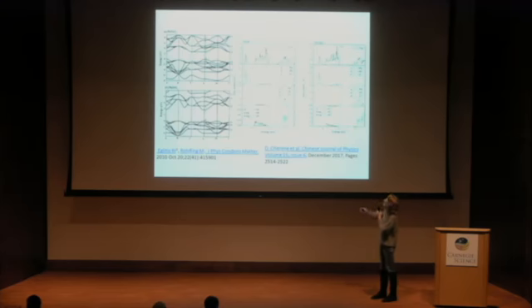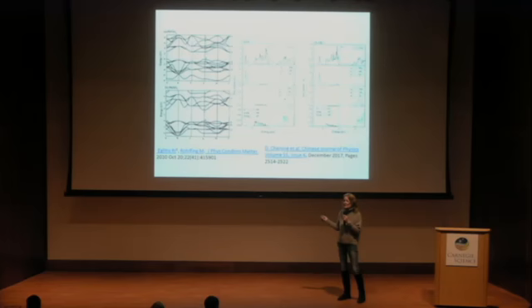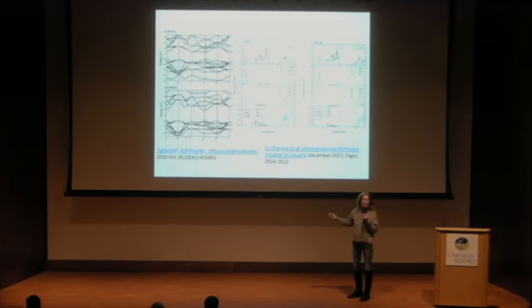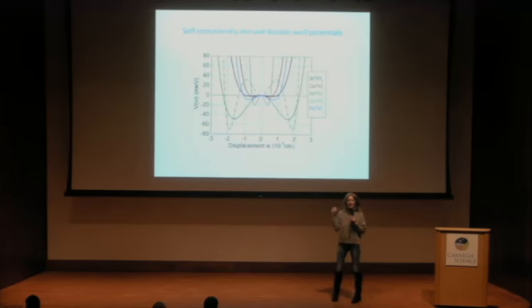But again, what is obvious in all these series is that the valence band is dominated by the p states of oxygens with admixture of the s states of lead. And again, the conduction band is almost exclusively made up of transition metal d states. The band gap, and this holds for all these compounds where you keep the A site intact, is systematically growing if you replace titanium by zirconium by hafnium. You can follow it through all 4 or 3 series which exist, but this is due just to the fact that you have a bigger volume and the d states are more expanded if you go to the higher homologs. So again, this is reference to the work, so it's really a lot of work being done on all these compounds.